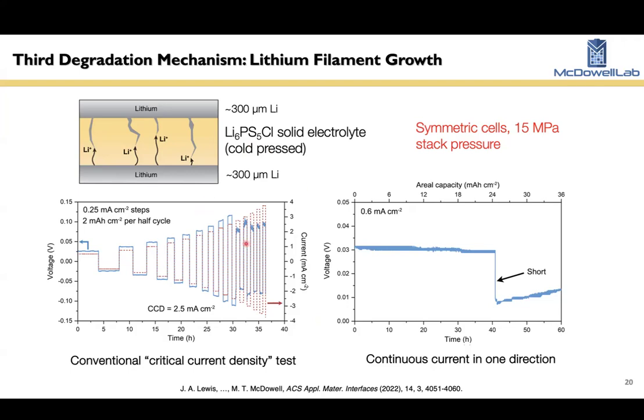And when you do these sorts of CCD, critical current density type experiments, you can get some value for the current density. But really, when you push lithium in one direction across a symmetric cell like this, what you find is, regardless of the current density, you will always eventually form a short circuit. We tested dozens and dozens of these cells, and we always found a short circuit. You might have to pass quite a lot of lithium. In this case, there's over 100 microns of lithium being passed, but you will always have a short circuit.